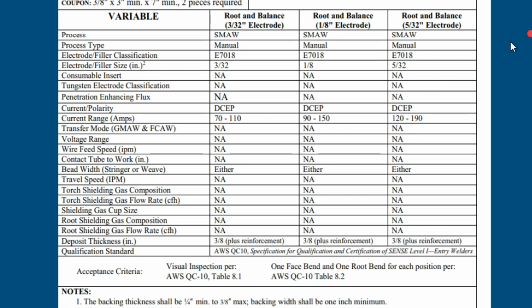So you can kind of see here, we've got your amperage range for a 3/32 between 70 and 110, and between 90 and 150 for an 1/8 inch electrode. I typically don't have anybody run a 5/32. We have a few electrodes in 5/32, but we just don't run them as often. But certainly it would save you a little bit of time if you jumped up to that.